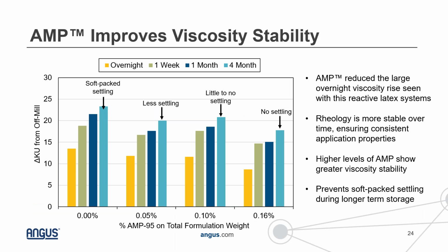And so what did we observe with some of these different paints? One of our first observations was that the paints that contained AMP showed improved viscosity stability. This is a plot looking at the Ku viscosity, either overnight after the paint was made, 1 week, 1 month, and 4 months of room temperature storage. And what we see immediately is that we don't see such a large viscosity rise overnight in the paints